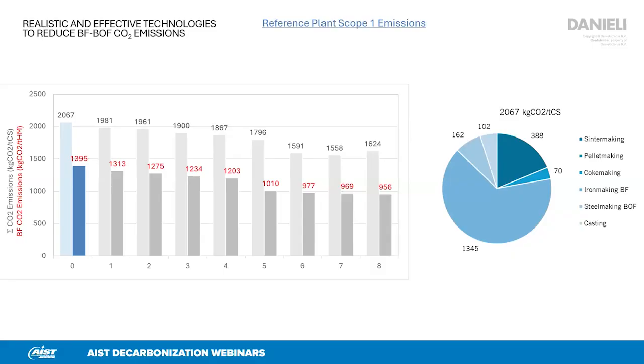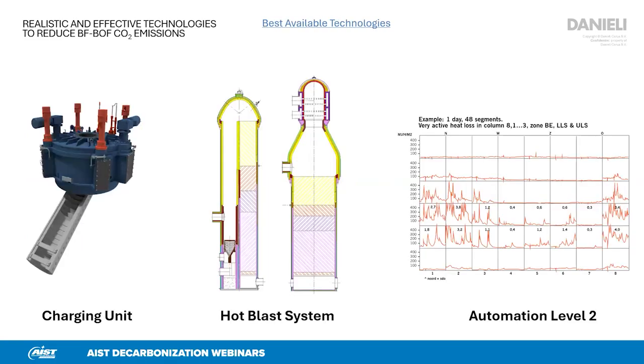And by the end, I will also share a forecast because that number could be even more reduced in another few years. How could the number of 2,067 kilos of CO2 be reduced right away? Well, there are 2 methods to reduce these emissions right away. That is first to implement best available technologies. And 3 such examples are summarized on this slide, which is a modern charging unit to reduce the coke rate by more optimum burden distribution and maximize the gas utilization.